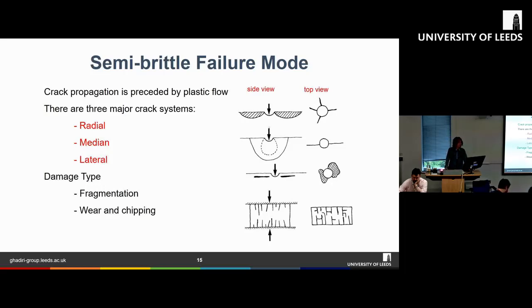So there are three major crack systems, as you can see here. We have radial, median, and lateral cracks. For the radial crack, from the top view at the site of impact, you can see that the crack propagates radially from the site of impact. And then look at the side view. This is how it propagates beneath the surface. Then the median crack basically goes all the way beneath the site of impact. And from the top view, you can see a straight line like this.